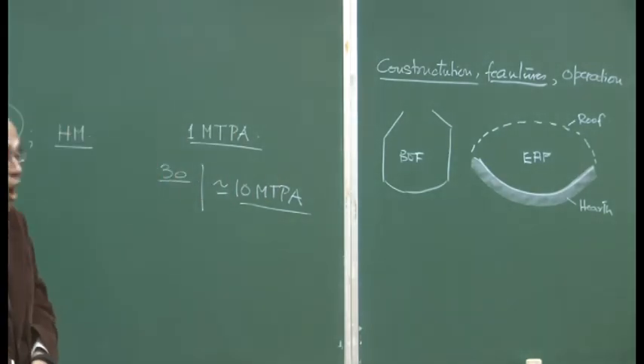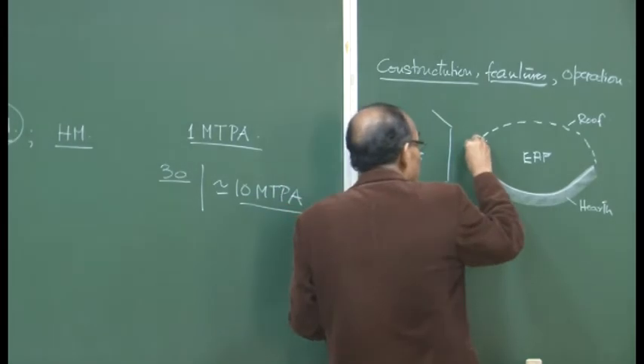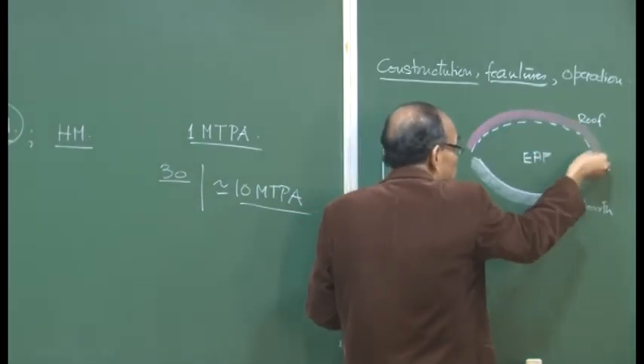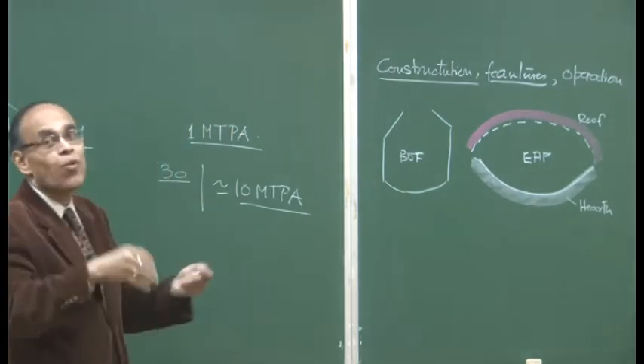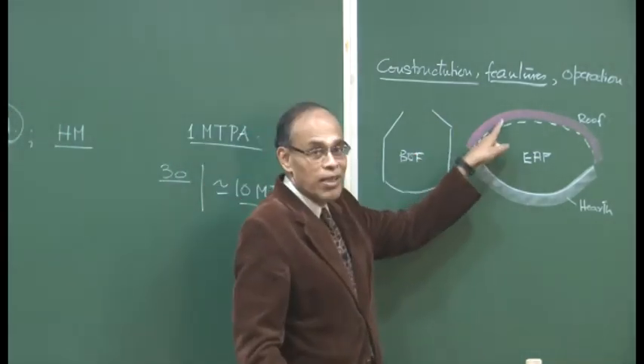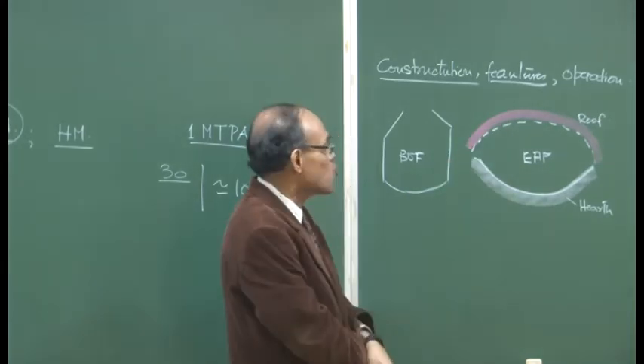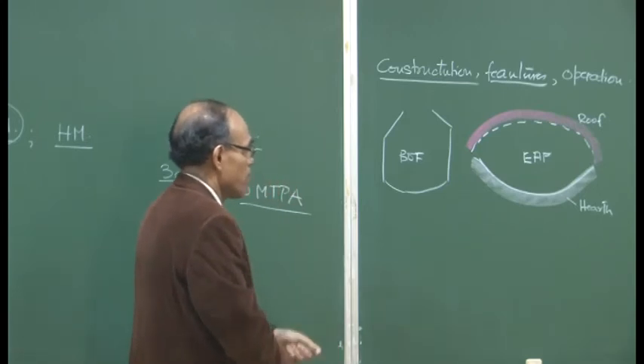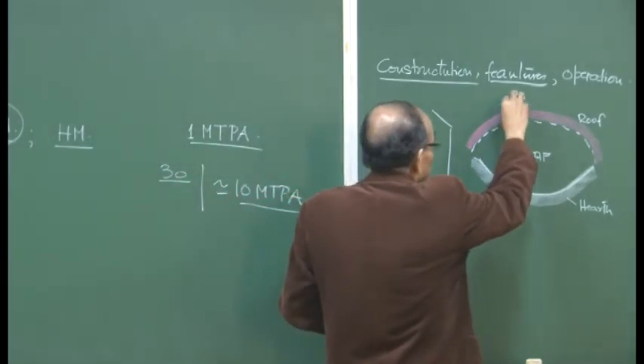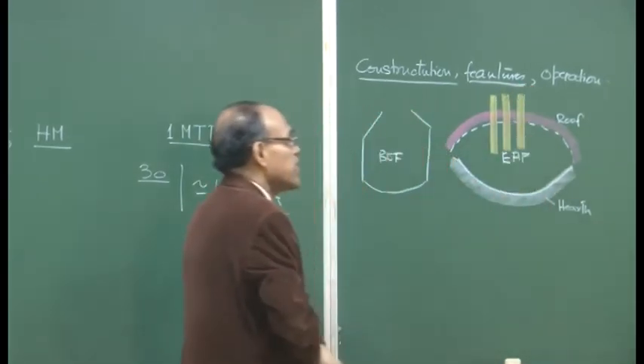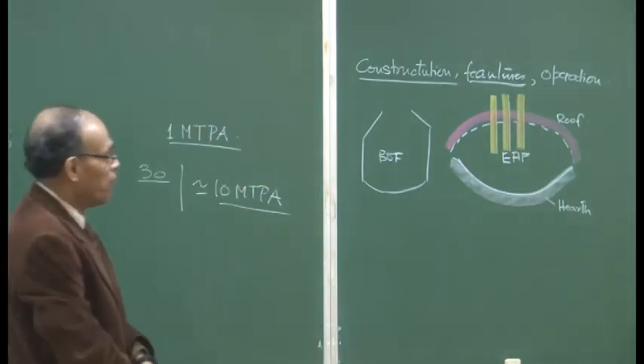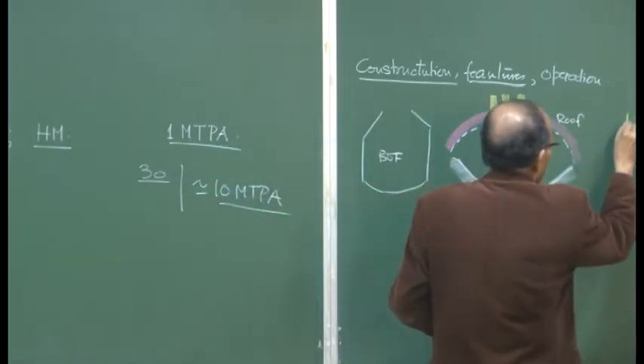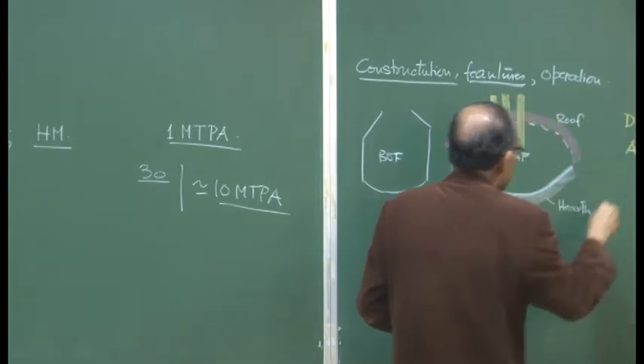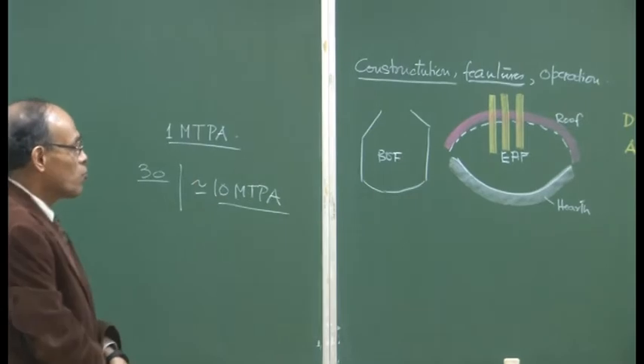Our requirements of lining materials are different in the roof as well as in the hearth, because of their exposure. The roof is not in touch with molten metal, but it is exposed to a huge amount of heat which is liberated from the system. Now, into it there are electrodes, and depending on the type of the furnace, we have two different types of furnaces. One we call a DC furnace, the other is an AC furnace, and what I have shown here are the three electrodes corresponding to the three phases.